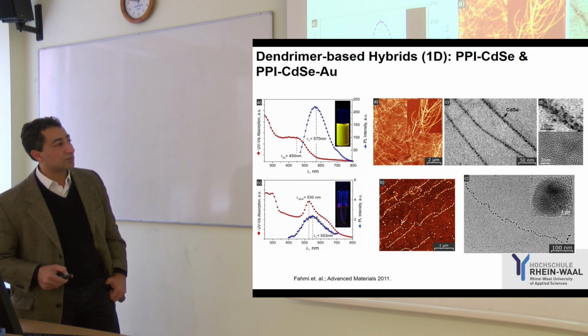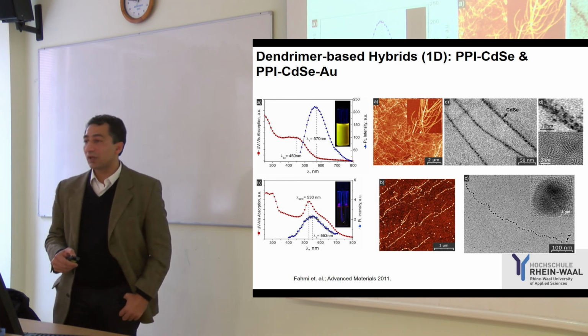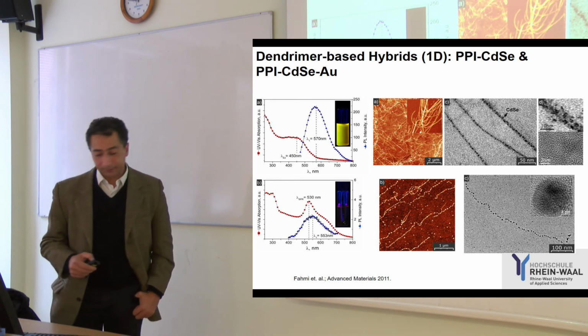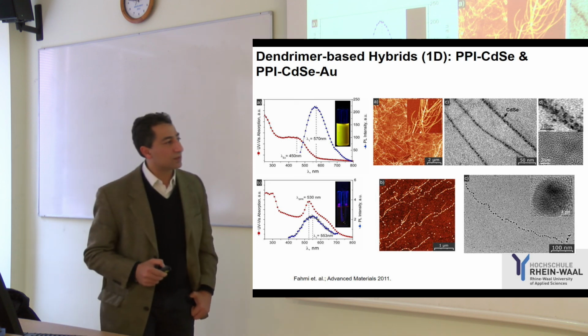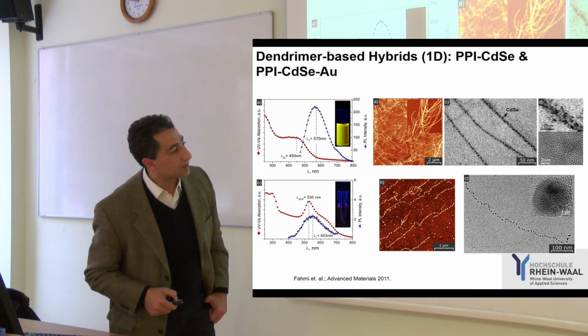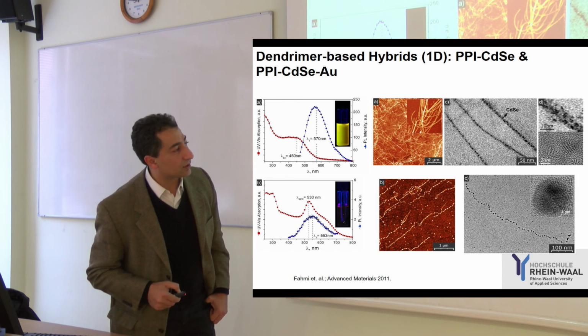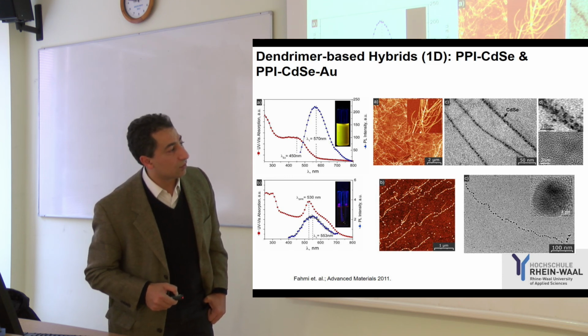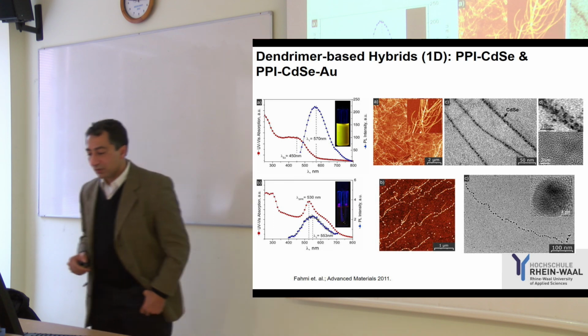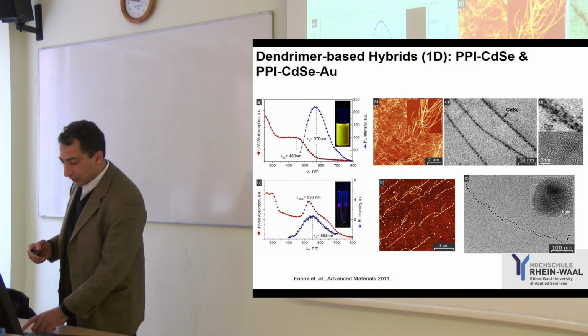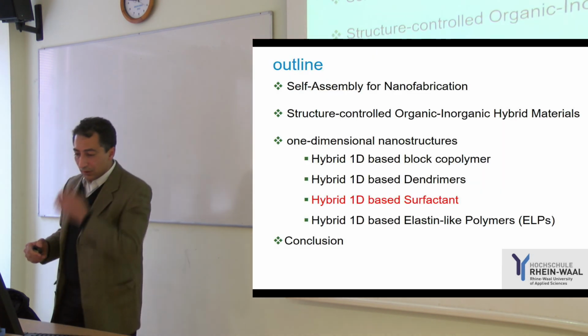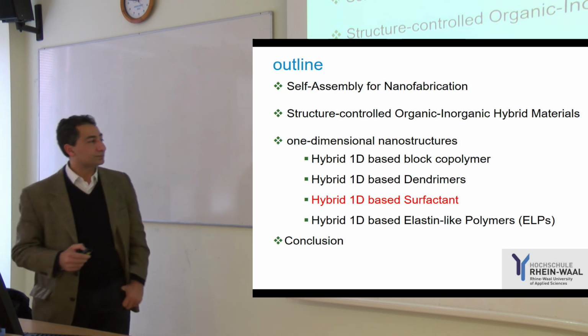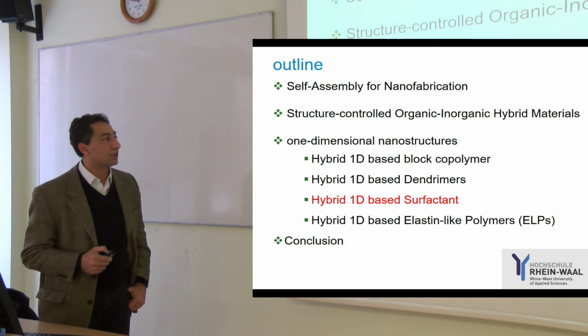After we put in the other metallic structure, we change the fluorescence. We can quench it to different levels, as you see here. The good news is that we have the bimetallic structure. Inside we have the inorganic semiconductors, and outside, as you see here, we have another metal aligned in a discrete manner on the one fiber structure. That was the second story.